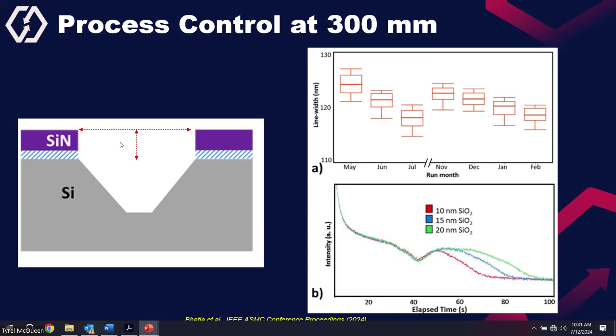For that, in the fab, we use optical emission spectroscopy, where they detect the reflected light and choose the wavelengths in such a way that when it reaches the silicon surface, we will know that it has reached the silicon surface and it will end the process. Here is an example of that. We use different thicknesses of silicon dioxide. For different thicknesses, we expect different endpoint times. As you can see, the time is increasing as a function of thickness.